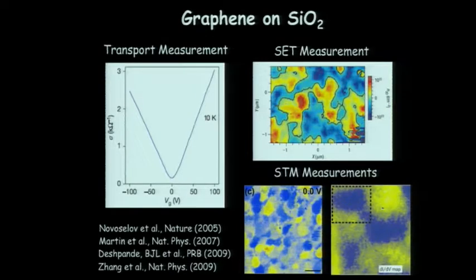Almost all graphene devices, from the very beginning when they were first exfoliated, were started on silicon oxide. The reason for this was that silicon oxide is a good substrate to be able to see graphene. You can identify it through optical contrast. But when you actually do a transport measurement here, looking at conductivity as a function of gate voltage, you see it takes a rather large gate voltage to change the conductivity.